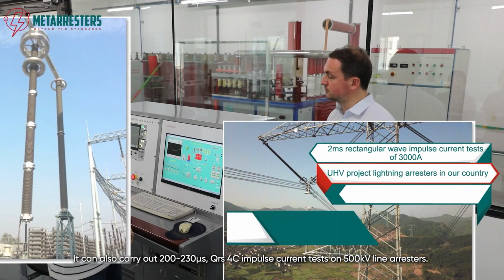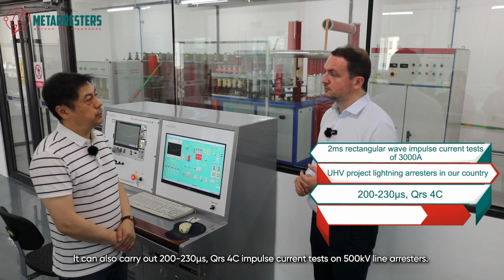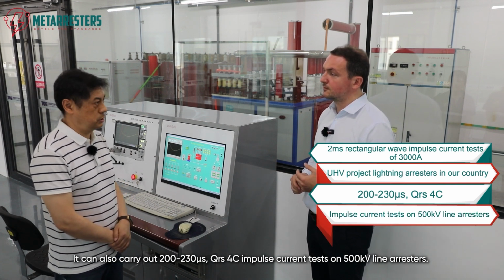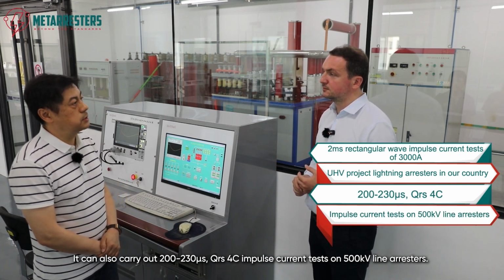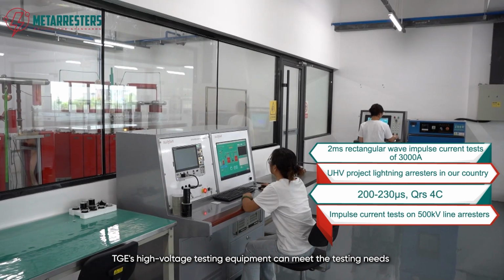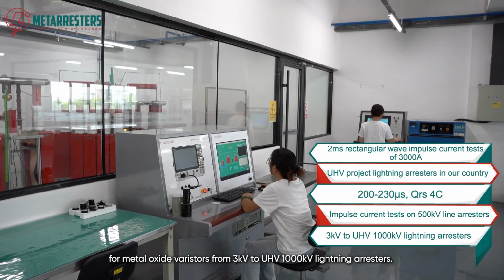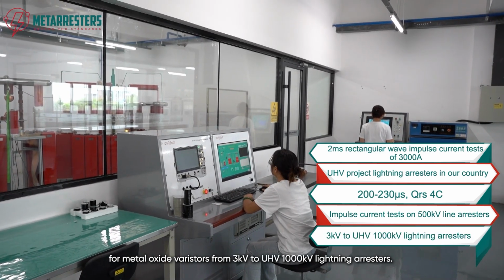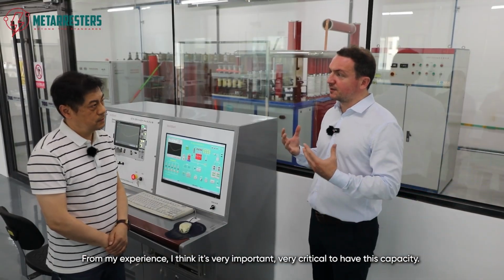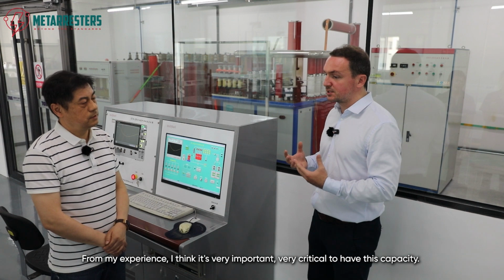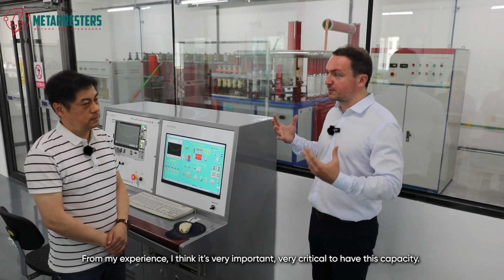It can also carry out 200 to 230 microseconds QRs 4C impulse current tests on 500 kilovolt line arrestors. TGE's high voltage testing equipment can meet the testing needs for metal oxide varistors from 3 kilovolts to UHV 1000 kilovolts lightning arrestors. From my experience, I think it's very important, very critical to have this capacity.